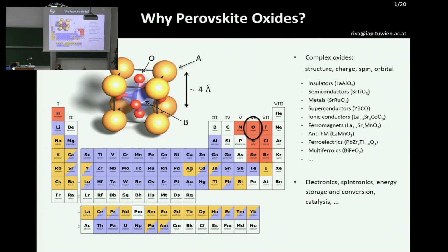So we're talking about perovskites. I'm sure I don't have to introduce perovskites so much to you. It's a structure based more or less on this cubic-ish unit where one atom type sits at the corner, another atom sits at the body center of the cube, surrounded by a cage of anions, in our case oxygen. The funny thing about perovskites is that you can more or less pick any 3 atoms from the periodic table, mix them up together, and they will have at least an allotrope that has a perovskite structure.